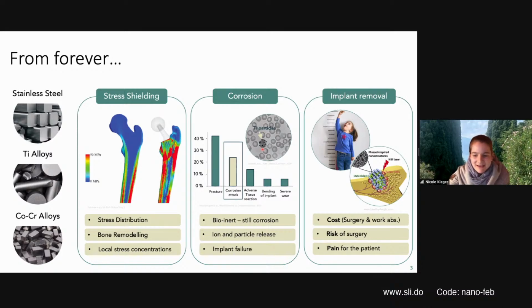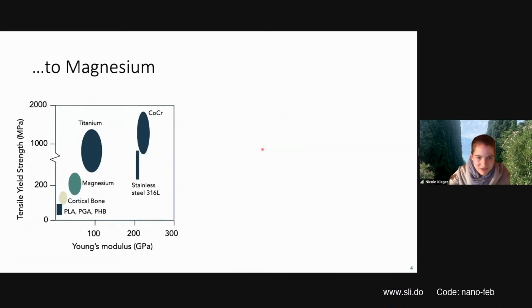So as I mentioned in the beginning, mechanical properties are really important. So let's have a look at the mechanical properties of different metals. So what you see on this chart here is the strength of the material versus the Young's modulus, which is a measure for the elastic property of a material. And what you can see here are the traditional materials in blue that I explained to you before. So chromium and steel, which are actually really strong and hard, and titanium, which is a bit closer to cortical bone here in this bone color. And what is really close to cortical bone is actually magnesium.